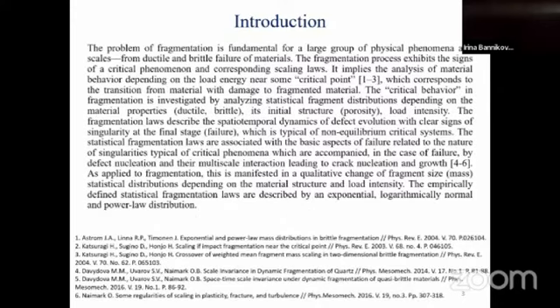In the introduction, the problem of fragmentation is fundamental for a broad group of physical phenomena at all scales, from ductile and brittle failure of materials. The fragmentation process exhibits signs of critical phenomena and corresponding scaling laws. It implies the analysis of material behavior depending on the loading energy near some critical point, which corresponds to the transition from materials with damage to fragmented materials. The critical behavior in fragmentation is investigated by analysis of statistical fragment distributions depending on the material properties, ductile, brittle, its initial structure, porosity, and loading intensity.